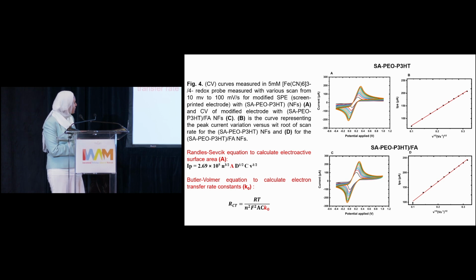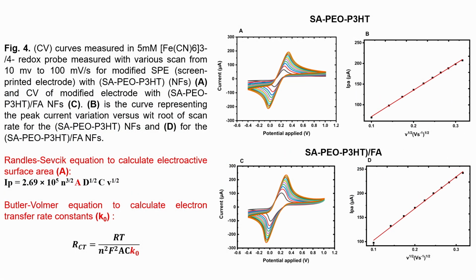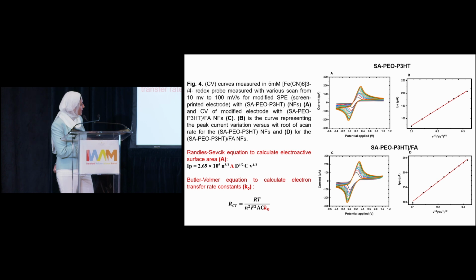From the slope of this curve, we obtained this equation, which is the Randles-Sevcik equation, to calculate a very important parameter, which is A, the electroactive surface area, which means the electroactive species allow the reaction between folic acid and folate receptors. The remaining terms are constants: the number of electrons, the diffusion coefficient, and the concentration of redox molecules, and we obtained an increase in this value. Also, from the Laviron equation, we calculated the constant for electron transfer. This parameter is also very important because it reflects the speed or kinetics of electron transfer in the electrolyte solution. And of course, if there is an increase in both these parameters, the electroactive surface area and the electron transfer constant, this confirmed enhancement of the sensitivity and amplification of the signal of our biosensor.